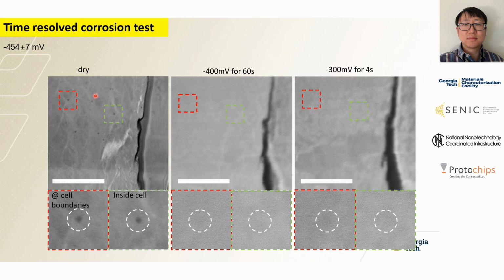In the first area, there is a dark spot, which from the EDS mapping we characterize as oxide. And this oxide is sitting at the intersection of the dislocation cell boundary. And in the second area, there is oxide just inside a dislocation cell. And we immerse this one in the hydrochloric acid and apply the voltage at minus 400 millivolts for 1 minute.